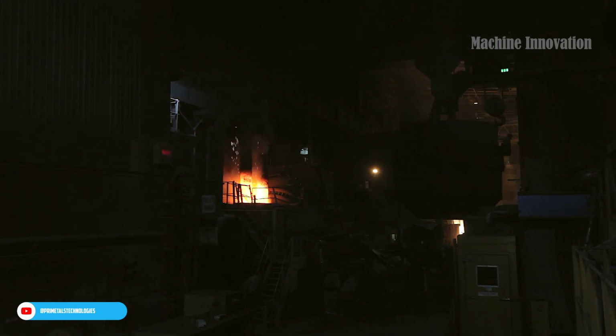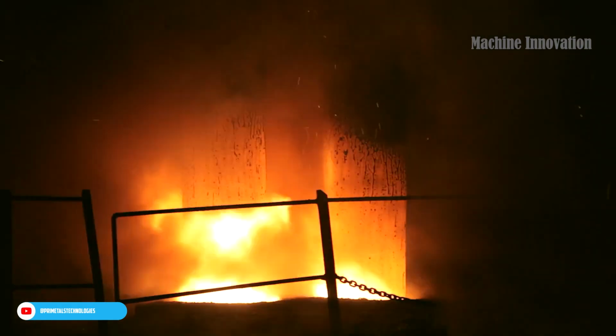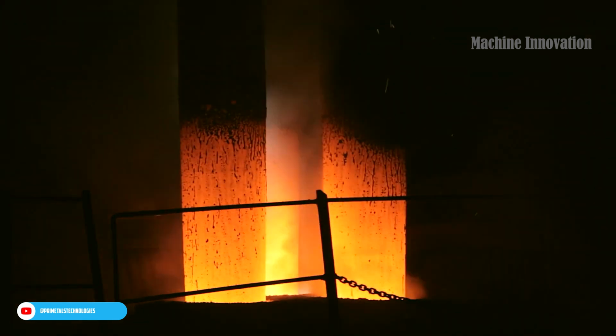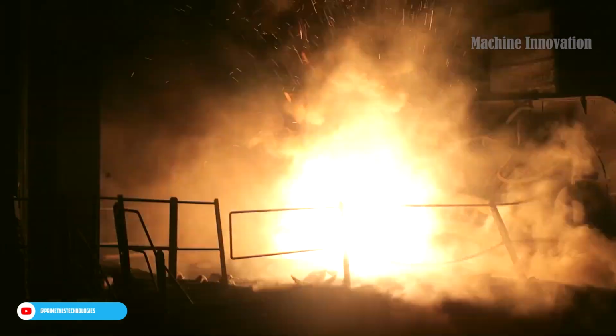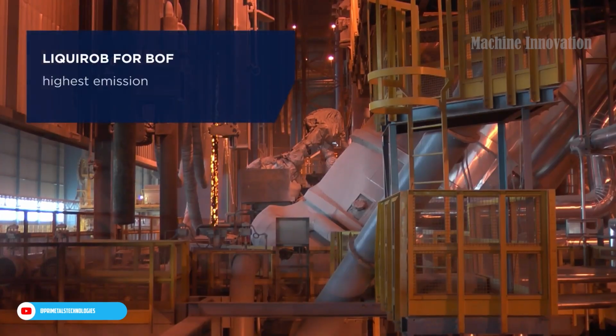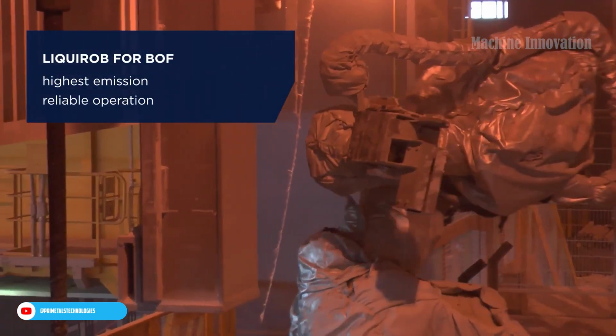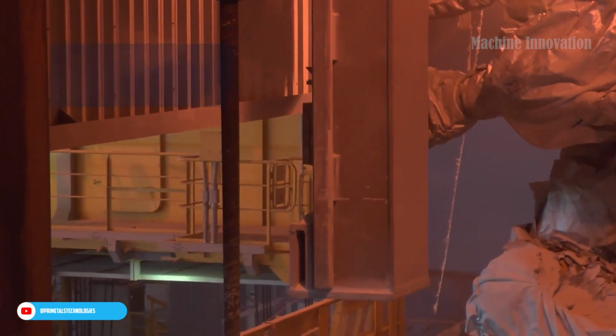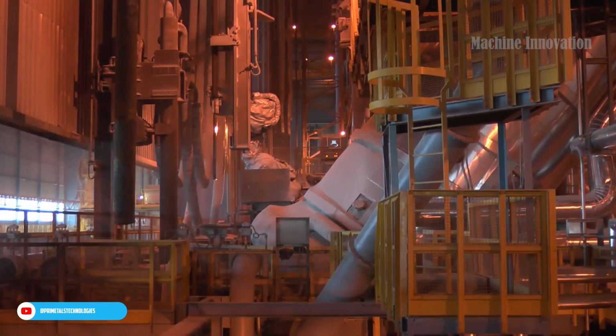Scrap steel is added to the BOF, reducing the reliance on raw iron and increasing the overall sustainability of the production process. The molten mixture undergoes a controlled burn-off process, where high temperatures remove impurities such as sulfur and phosphorus. This refined iron, now transitioning to steel, has reduced carbon content and improved purity, characteristics essential for creating high-quality steel.